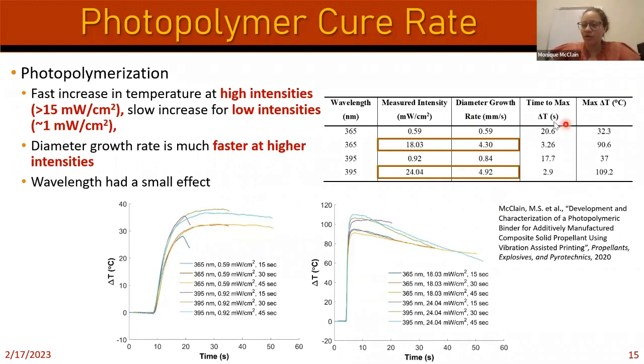And then finally, here are some other data points. How long did it take to reach that maximum temperature difference? For these higher intensity ones, it was relatively short, and for lower intensity, it took much longer. Then we calculated that maximum temperature change. You could see that for the raw photopolymer, it could get pretty hot. However, when we did this for the actual propellant mixtures, it was much lower temperature. So it wasn't actually a concern for us for energetics. It was not hot enough to make it ignite. So that was a good thing.